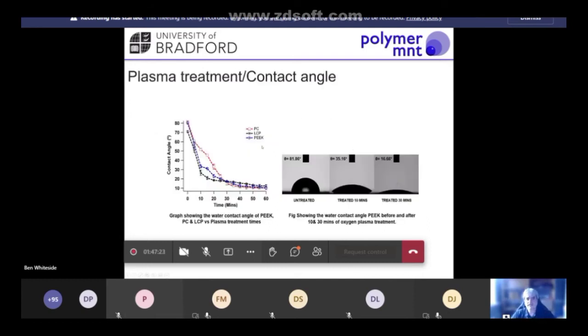Just to give an example of how it can improve the contact angle, this was an example where we wanted to coat a PEEK microneedle array. So what we did was we looked at contact angle measurements before and after oxygen plasma treatment. And you can see that after 30 minutes of plasma treatment, we get significant improvements in the contact angle, a significant increase in surface energy. So we're able to get things to stick more easily to these surfaces.